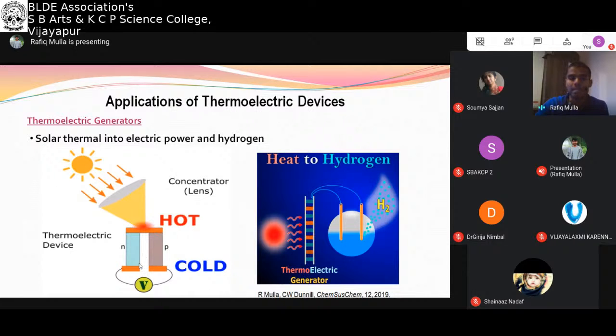So here, again, the concept is very simple. We have this device, and we need to have some temperature gradient across the device, and this temperature gradient can be created by solar radiation. But directly using solar light will not produce enough temperature gradient across the device, so one can use concentrators or lenses, and by using a lens, we can focus the solar radiation into high density light, so that it produces more heating effect on the hot side, on the top surface of the device, and because of that we can achieve a better temperature gradient. So this surface works as the hot side and this as the cold side,